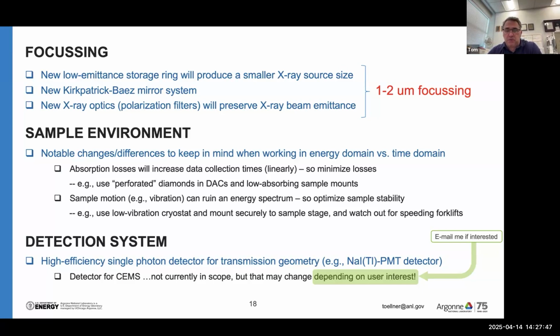Another issue is vibration. In time domain, you don't have to worry about vibrations at all. In the case of the energy domain, vibrations can ruin the spectrum, and so one has to consider using low vibration cryostats and also mounting samples securely on a mount so that they cannot vibrate. For the detector, we'll just use sodium iodide. We need photon counting capability, but we do not need any timing capability.